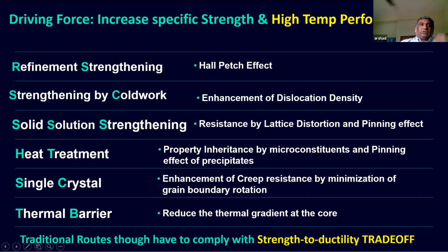Now, the main objective for the superstructure is weight reduction, and weight reduction directly relates to the specific strength of material. Typically, conventional strengthening comes with four aspects: grain refinement strengthening, dictated by the Hall-Petch effect, and strengthening by cold work, that is facilitated by enhancement of dislocation density. A fully annealed material will have a dislocation density of 10 to the power 8, and when you give it heavy cold work, it will increase to 10 to the power 12. So this is the order of dislocation density that changes as a result of cold work. Cold work enhances dislocation density, which in turn enhances the strength of material.